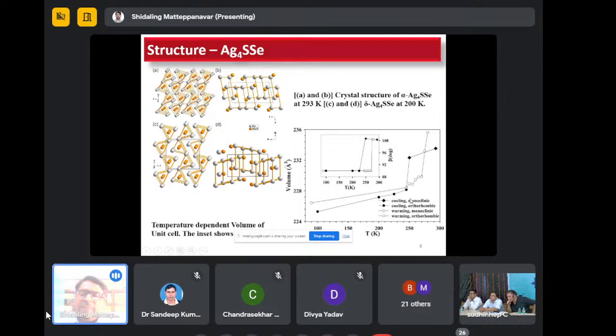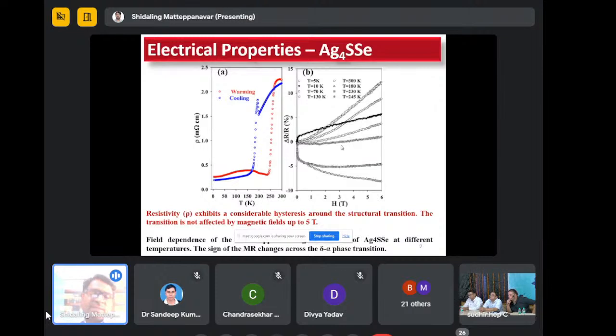The transition is very sharp at around 250 K, and all the atomic parameters we extracted by fitting with the JANA software, and they showed that there is a clear structural transition happening from the monoclinic to orthorhombic. And then basically we are interested to see how this structural transition affects the electrical properties.